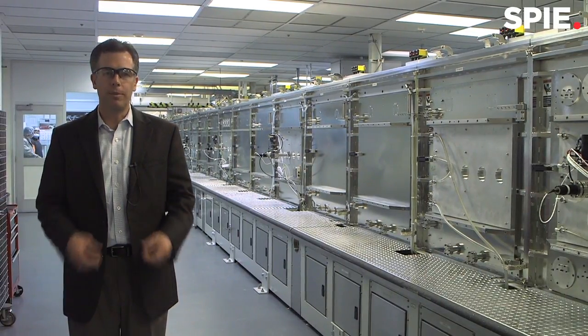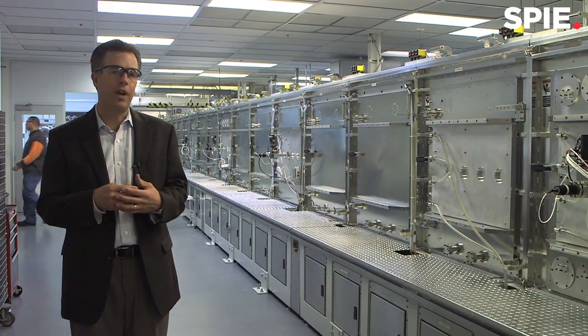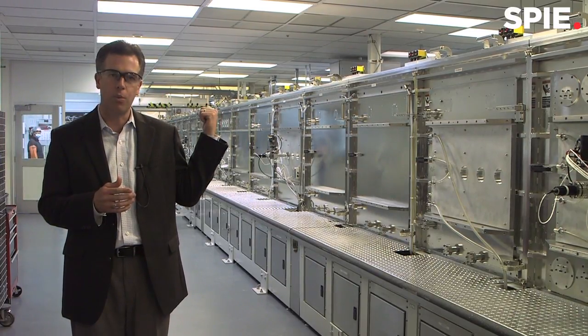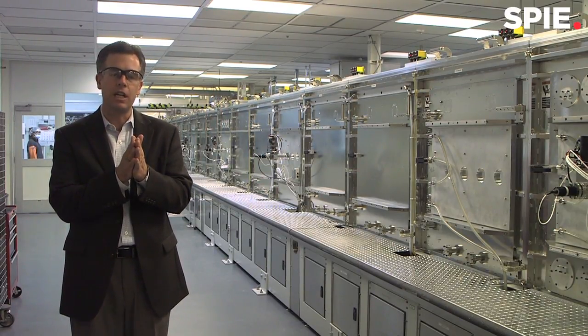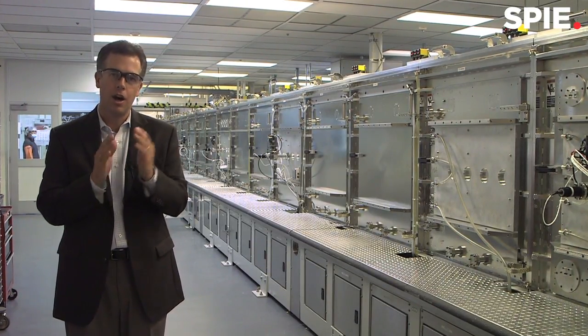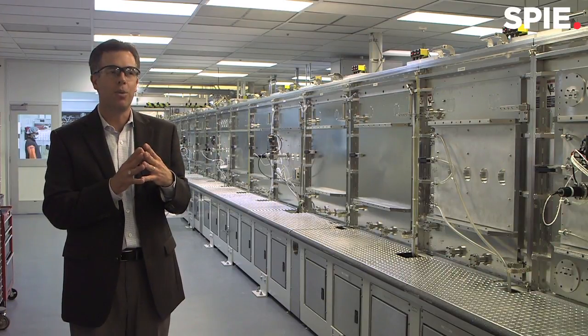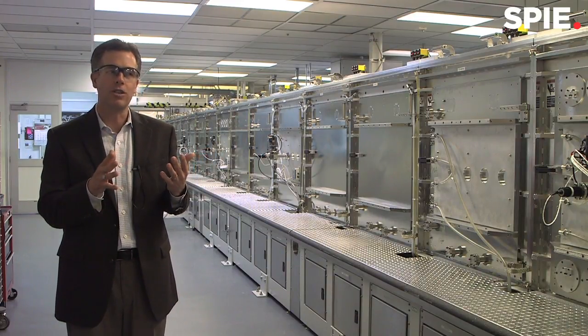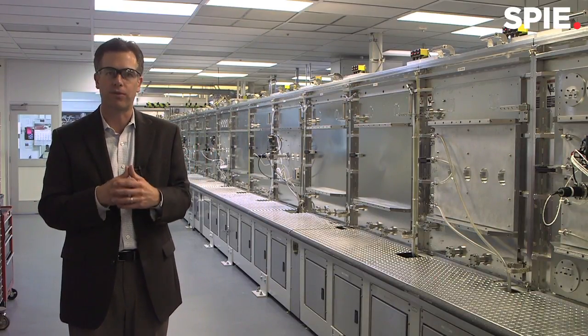As part of the scaling-up development from simple two-inch samples, we were lucky enough to find this facility with its existing physical vapor deposition — or sputtering — piece of equipment. This is an inline sputtering tool where you put a substrate in one end, and as you progress through the tool, you can deposit different layers by PVD or sputtering. At the end, it comes out with a layer of thin film typically about a micron thick on the glass. This tool was used previously for a different industry, but it's a great R&D tool that we repurposed to deposit inorganic metal oxide materials onto glass for our technology.